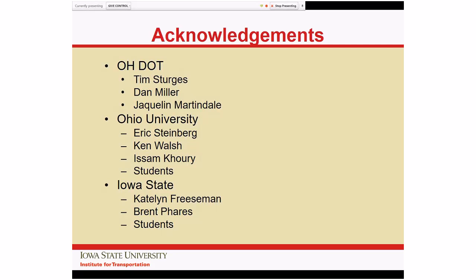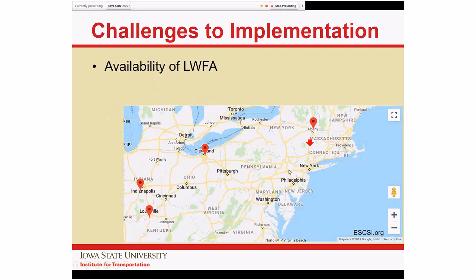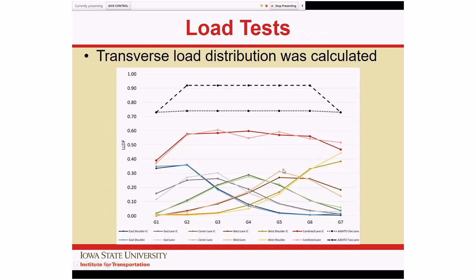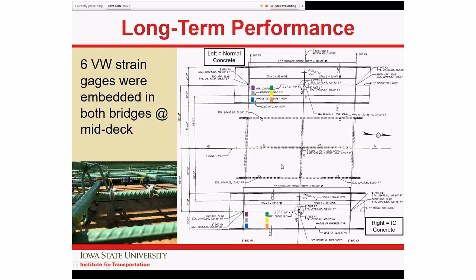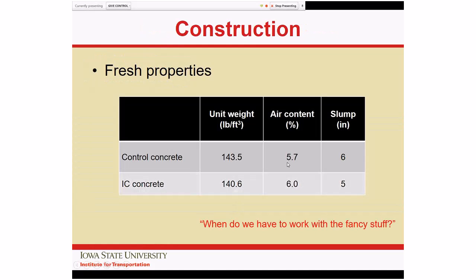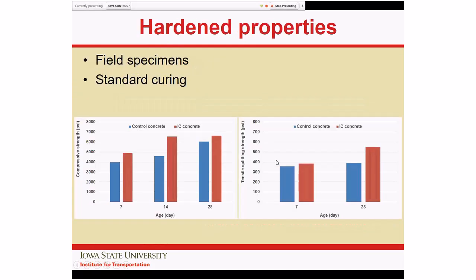I'm wondering, you said the flexural strengths were lower. Were there 7-day breaks done on test cylinders? I'm pretty sure there were. Is this an issue because slag tends to build strength at a slower rate? So there's no alarms. No, we've got flexural at 7-day. The tensile was actually higher for the field samples.